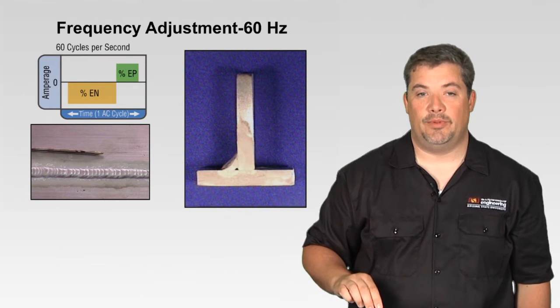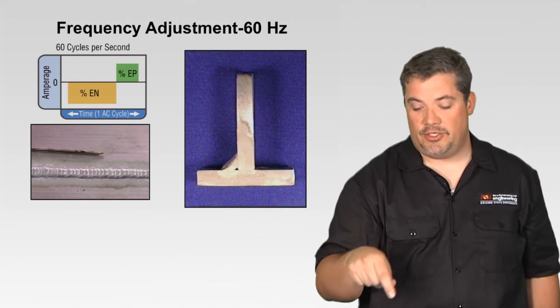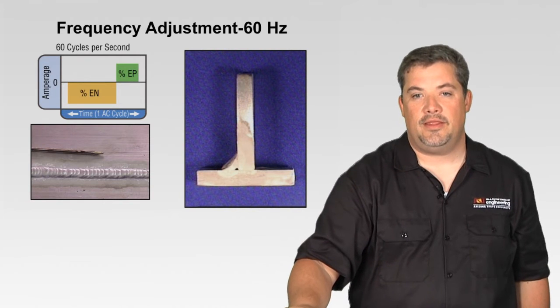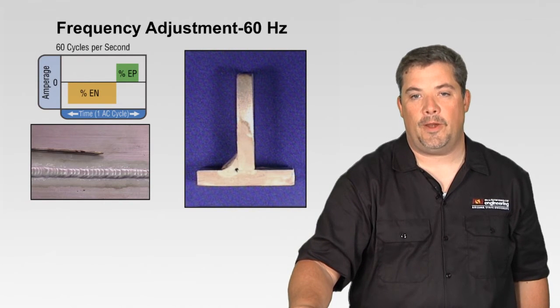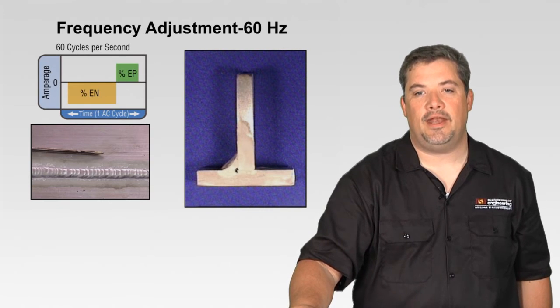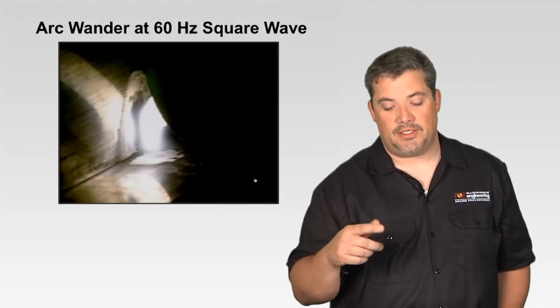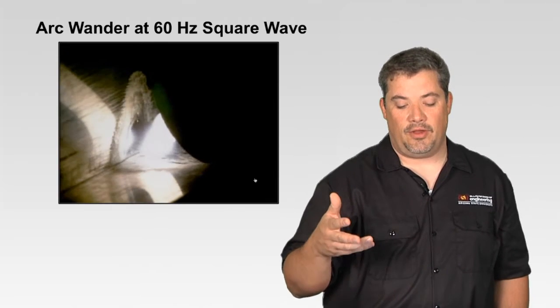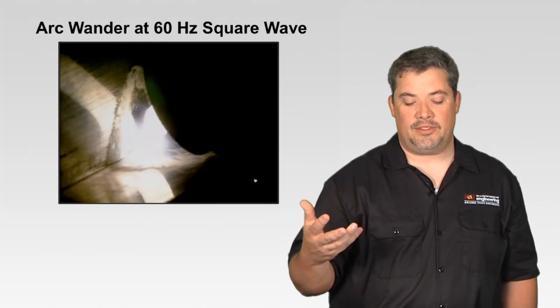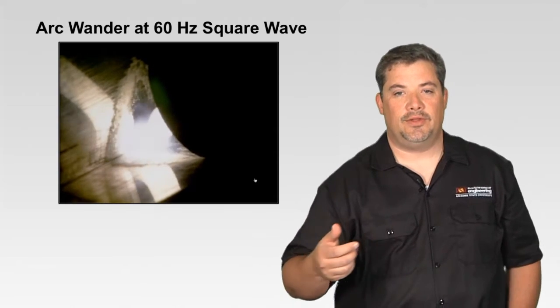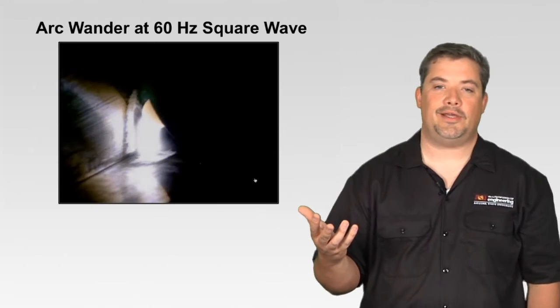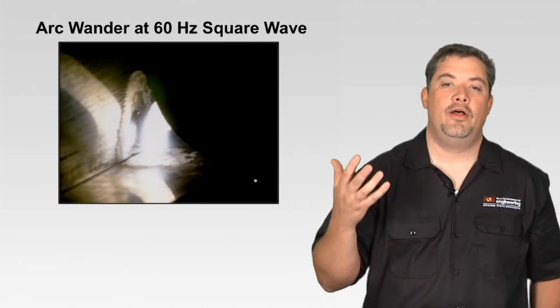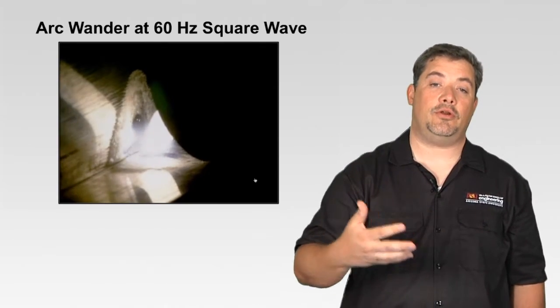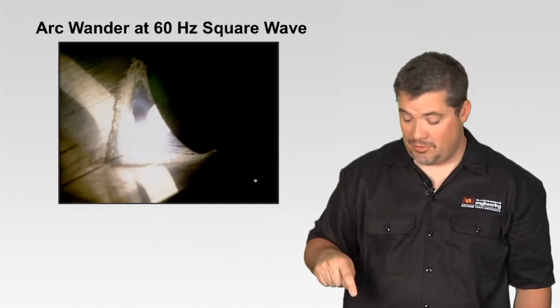So looking at frequency adjustment, a great visualization is, here's a T-joint, 3/8 wall. You can see in this illustration some incomplete root penetration in the corner of that weld joint. We have to break down that very corner. Well, this is easy to get in an old school machine, and this video shows why. With that large ball in the tungsten, this is high-speed video, that AC current going from positive to negative, that electricity is taking its path of least resistance. So in this case, off the end of the ball, it's going wherever it wants off the end of that ball. I really don't have the directional control and stability to ensure that I'm directing my heat energy where I need it to in that puddle.